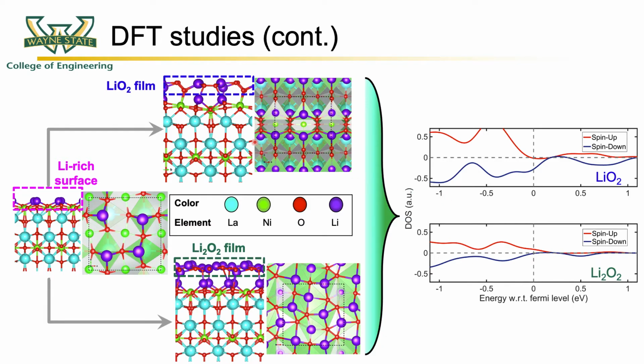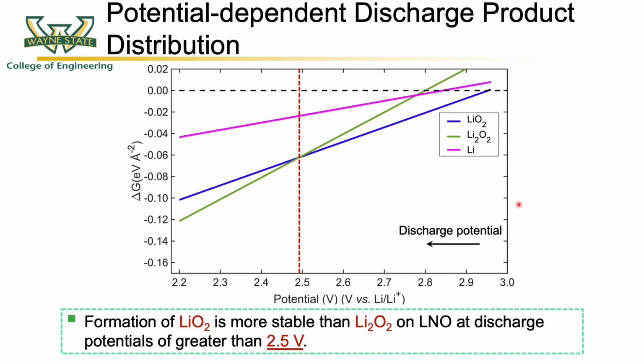To further understand the electronic structure of this interface, we use density of states analysis, where continuous states are found both for LiO2 and Li2O2 at the surface with LNO, thus suggesting a conductive interface potentially leading to lowering of the charge overpotential losses.